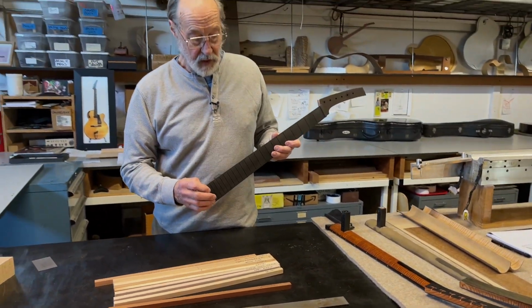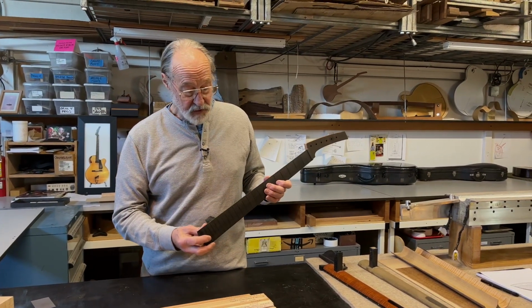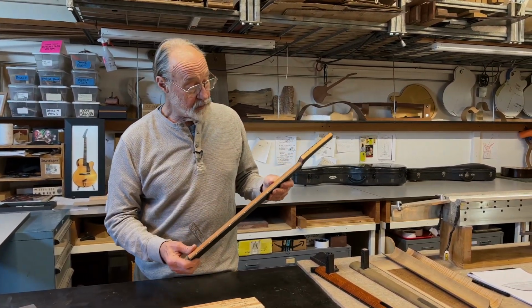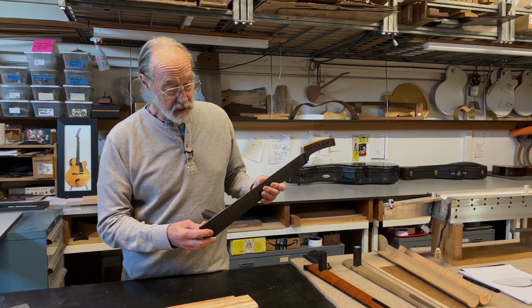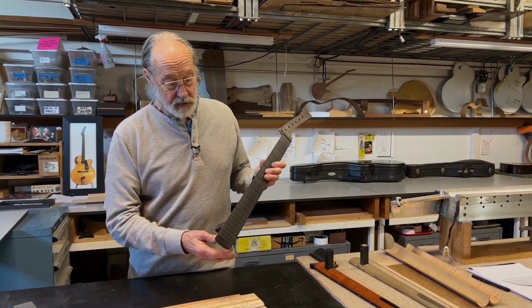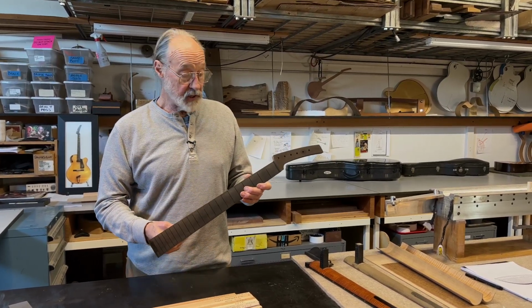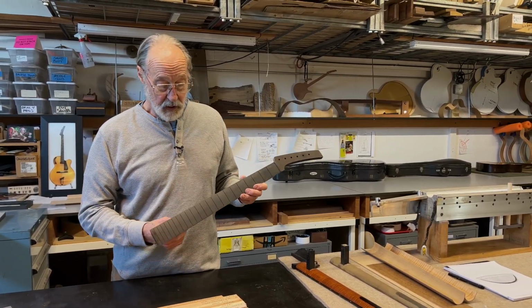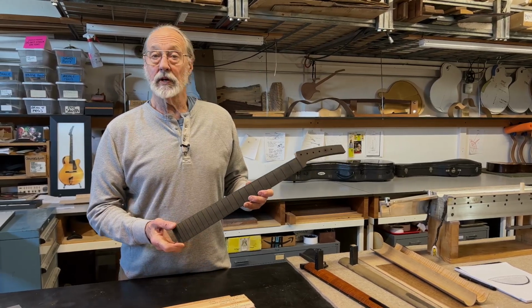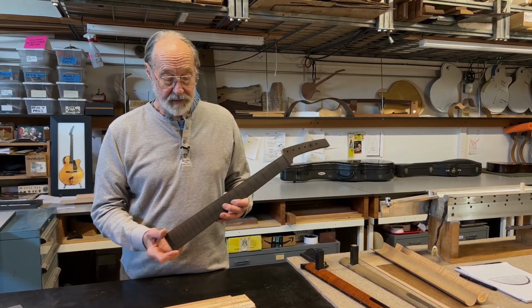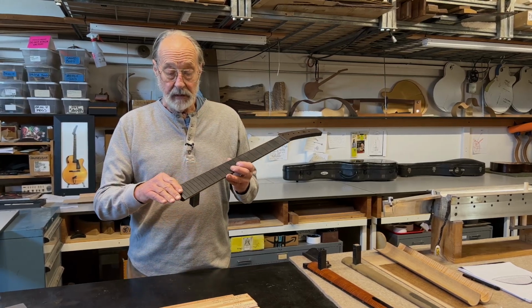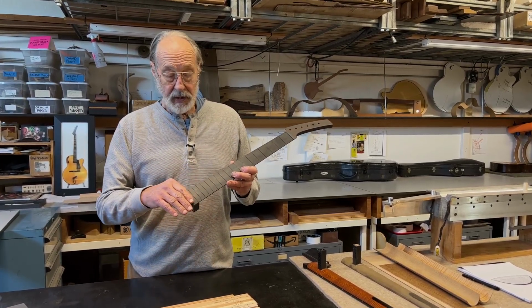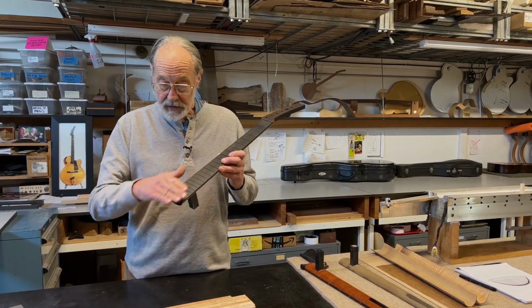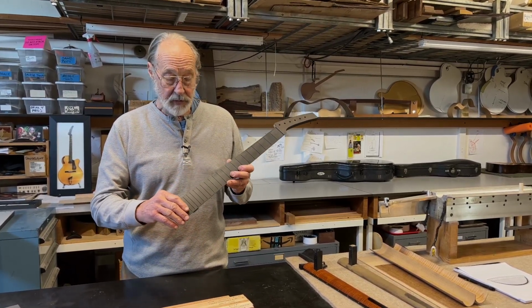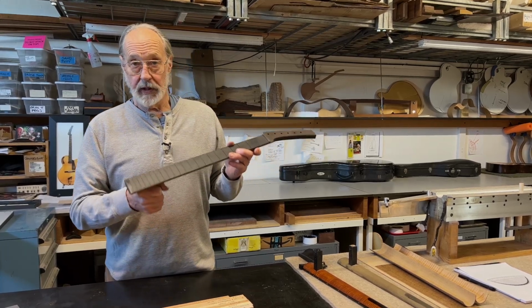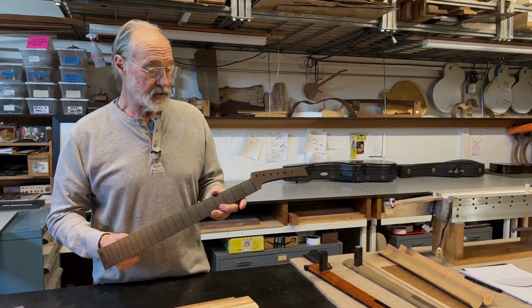So what we've done, this neck does not have an adjustable truss rod. That's not what I'm using anymore. I'll explain why in a little bit, but this neck is designed to pull up and be exactly the right shape that is very nearly straight so far as the string is concerned when the string load is applied to it. And that means that we have to anticipate the bending by shaping the neck accordingly. In other words, to let the end of the neck fall off or slope downwards a little bit so that when strings are applied, we get whatever it is we want, relatively straight condition, that is.